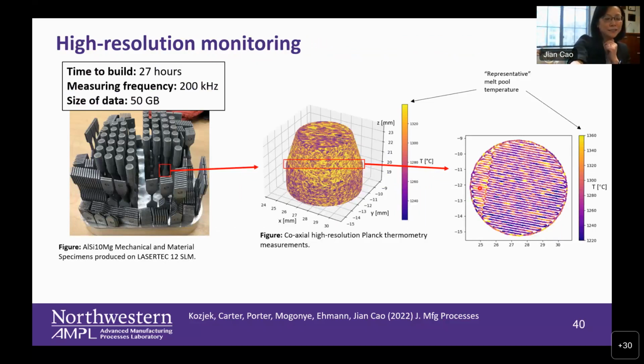For this one, it's easy in the sense that it's only a very simple geometry. In the recent paper, we look at all these different geometries, and you can see that the neighborhood as well as the previous buildup are very important. We show that we need the previous 20 layers, sometimes even 50 layers, in order to give a good prediction for the next layer.